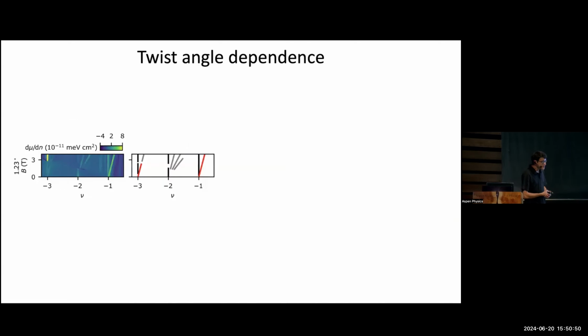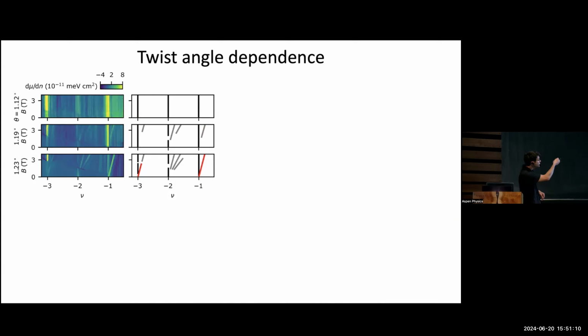So the nice thing about this sample, as I said, there's a variation in twist angle. So we can look as a function of twist angle, how does this topological behavior depend on twist angle, as we move our tip to different spots over the sample. This is just the data that I showed you before. Again, there are these diagonal features going all the way to 0 magnetic field. If we decrease the twist angle, even by a very, very small amount, actually incompressible states at nu equals 1 are vertical. So the state has gone trivial, no longer topological.